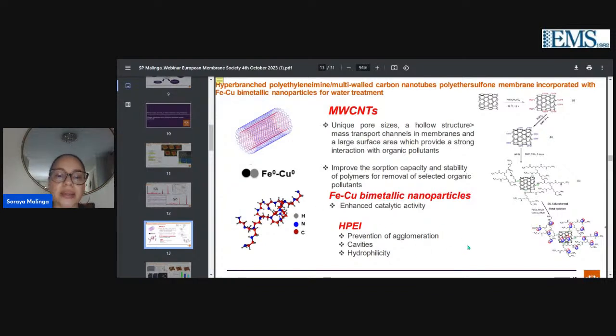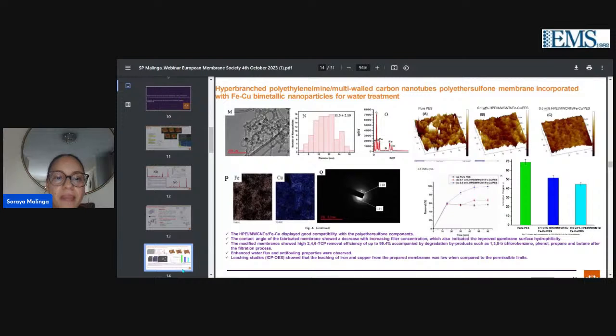Then we prepared the iron copper bimetallic within this composite. So it was a composite. Then we embedded it via the phase inversion method on a membrane. So hence I have indicated that the properties we were looking for from the hyperbranched polymer were prevention of agglomeration, the presence of cavities, and the fact that they can induce hydrophilic properties on our membranes.